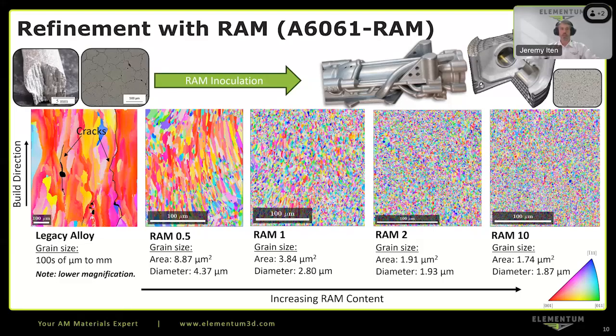So because of this, most of these traditional, very desirable high-strength wrought alloys for aluminums and many other materials are unprintable or unusable today without changing something. So we've been able to use reactive additive manufacturing to make these alloys printable with properties that meet or oftentimes even exceed their wrought legacy counterparts. In the colored images there, those are EBSD images showing the grain structure of the printed materials.